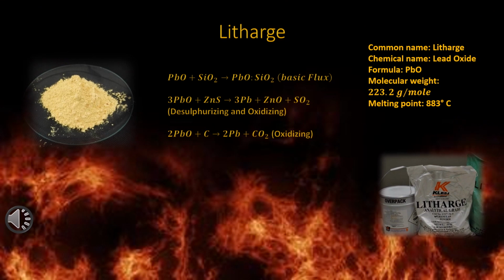Lead oxide, commonly referred to as litharge, comes in a granulated and powdered form. It is classified as silver-free. However, there will always be a small concentration of silver. When this material arrives at the lab, it will always be tested for the silver concentration. As a small prospector or small-scale miner, you will not be doing any critical analysis and therefore preliminary testing may not be considered. Litharge is readily fusible.